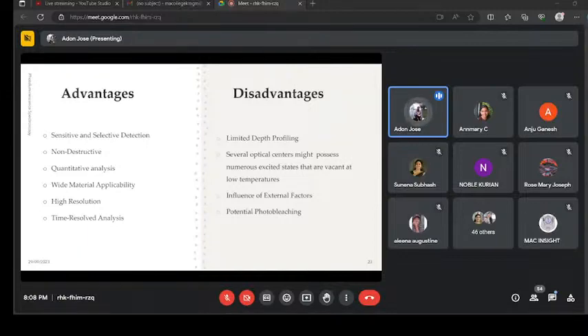we can get a complete idea of that luminescence behavior by using this spectroscopic technique. But the major disadvantages of this spectroscopy that we usually face are the several optical centers that might possess numerous excited states that are vacant at low temperature. It is found to be difficult, and there is limited depth of profiling. That means photoluminescence spectroscopy primarily provides information from the surface of the sample, limiting its ability to probe the internal structure or properties of thick or opaque materials.